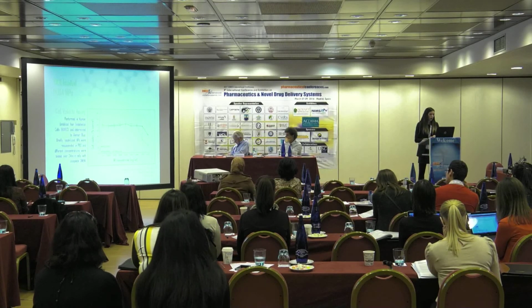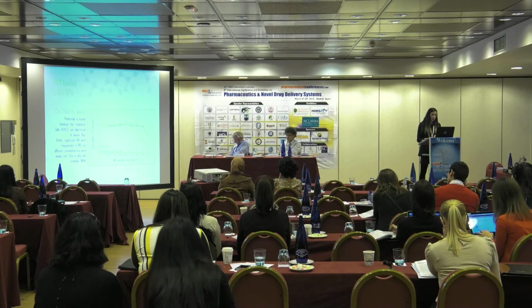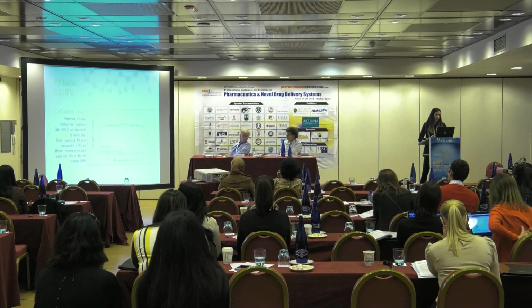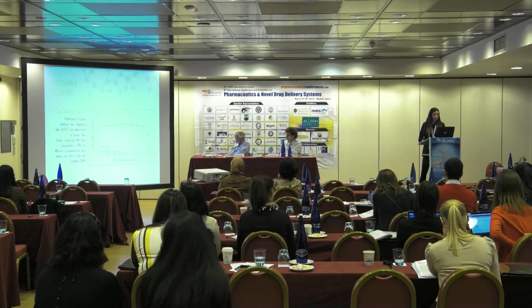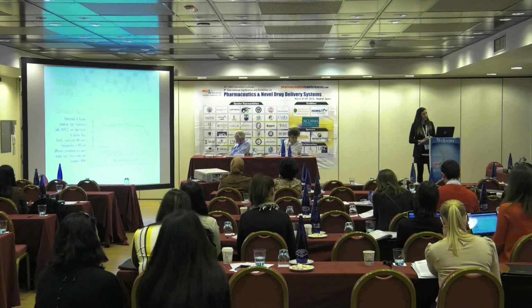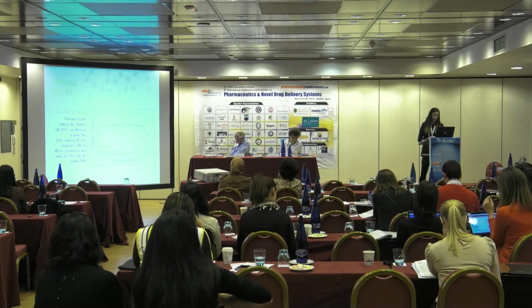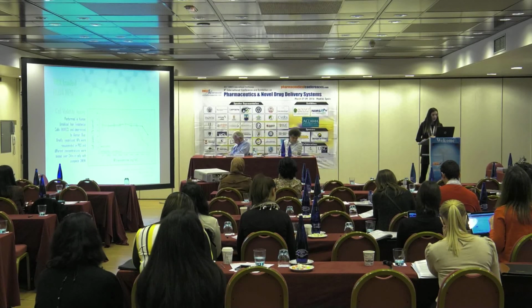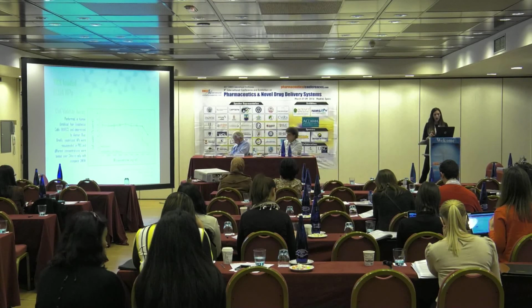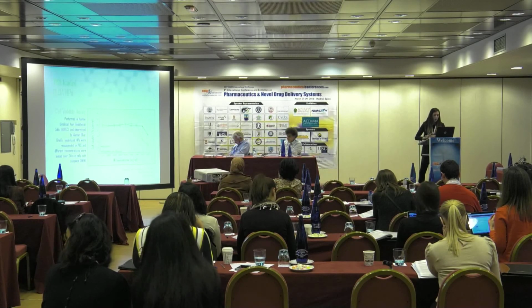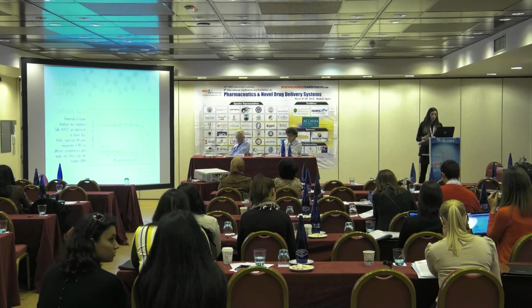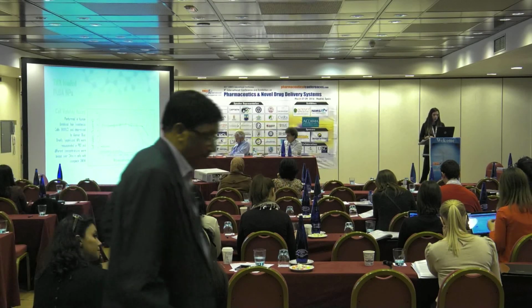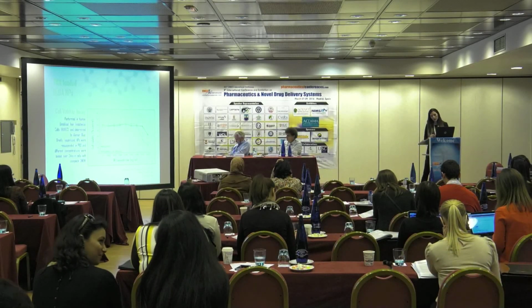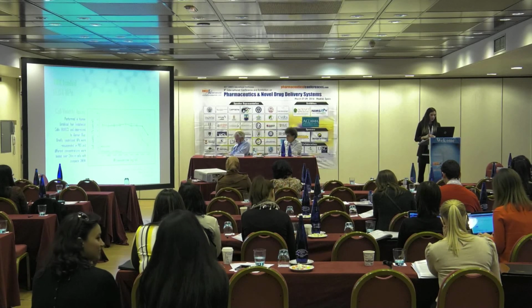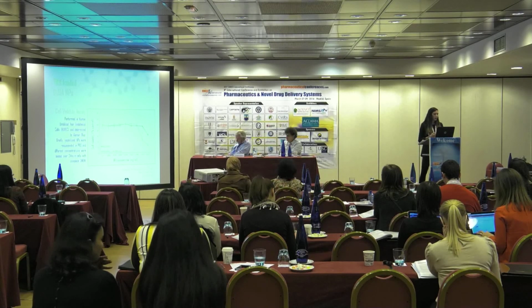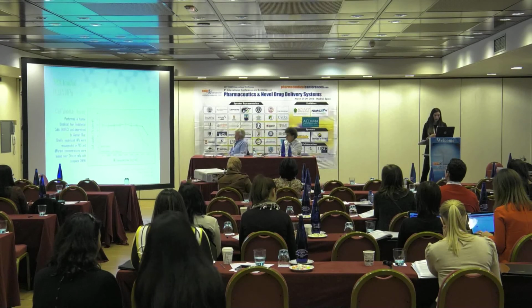With these particles, we did a collaboration with the biomaterials group in the Institute of Science and Technology of Polymers here in Madrid. And what we saw is that when we tested the PLGA particles loaded with tamoxifen in human umbilical vein endothelial cells, and compared the empty PLGA nanoparticles with tamoxifen-loaded nanoparticles, in the two more concentrated suspensions of nanoparticles we see a statistically significant difference. So we see that in these two concentrations, the nanoparticles loaded with tamoxifen are in fact toxic.